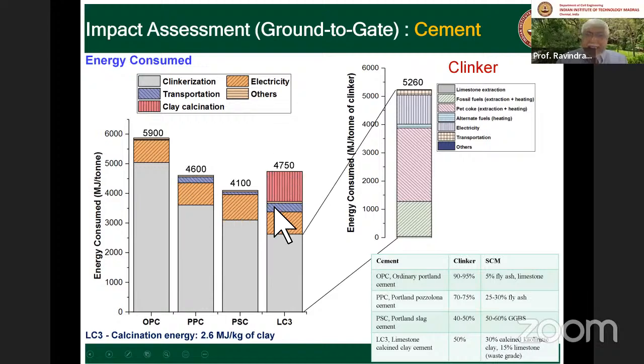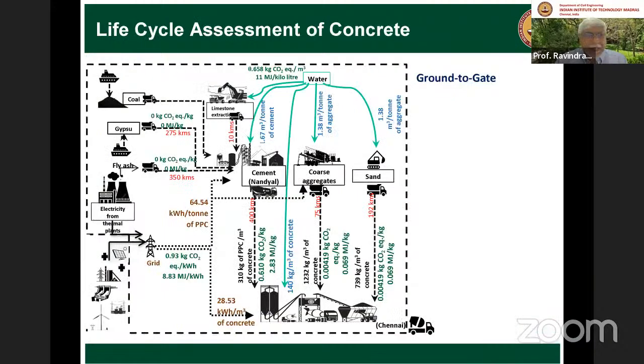With LC3, there is some requirement of calcination, which makes it comparable overall to PPC, but it is significantly less than what is required for OPC. And on the right, you have the breakup for the clinker. So most of the energy in India, in this plant in particular, comes from the burning of pet coke and other fossil fuels. And there is some part which is also coming from the electricity requirement for the grinding and so on. So clearly you see that when we use LC3, we have a huge reduction in the emissions and the energy requirement. Let's look at concrete.